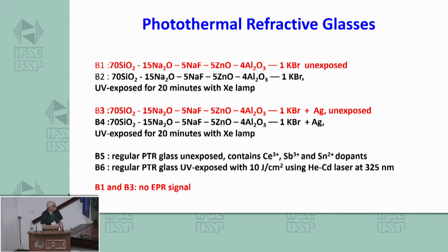And then what was found is that it works particularly well if you have a little bit of antimony, cerium, and tin, preferably all of it, also present. And that was always kind of a little bit magic. Why we need these dopants for facilitating the crystallization, facilitating the glass. So the optimized composition always contains this. And what exactly these dopants are doing, we tried to address by EPR spectroscopy.